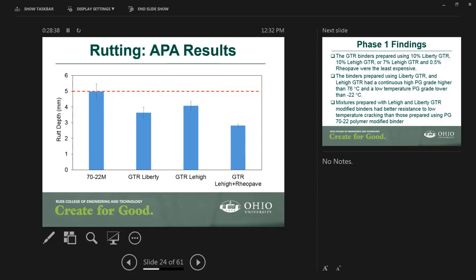Rutting. ODOT requires, for a roadway with medium traffic, which is the type of roadway that we're designing for locals, a maximum of 5 millimeters after 20,000 cycles in the APA. All asphalt mixtures have met that criteria, but with the GTR, as you can see here, we had a significant reduction in rutting, which means that the GTR asphalt mixtures have a better rutting resistance than the polymer modified, as indicated by the results of the APA.